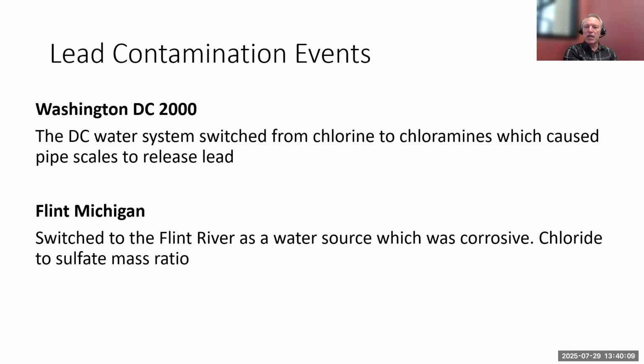Seemingly a pretty innocuous change, but it disrupted the pipe scales and led to a release of lead into the drinking water. In Flint, Michigan, they actually switched to a different water source, the Flint River. There was already a treatment plant in place there, a large treatment plant already set up. It turned out that water source was corrosive, and one of the factors that was used to analyze the corrosivity was the chloride to sulfate mass ratio. And both of these events actually ended up changing the way we approach the lead and copper rule.